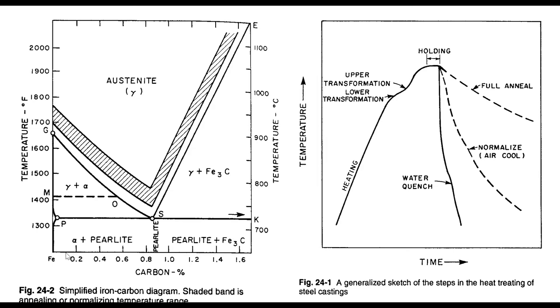My normal steels are between 0.1 carbon and 0.4 carbon. If I get much above 0.4 carbon, I have a real problem with the material cracking. I get much stronger, but the stronger I make the steel, generally the less tough it is and the less ductile it is.